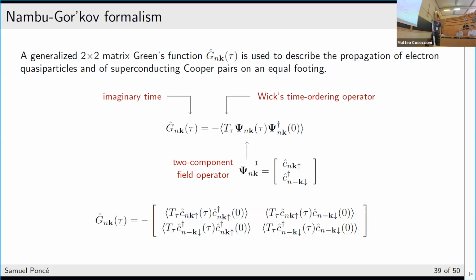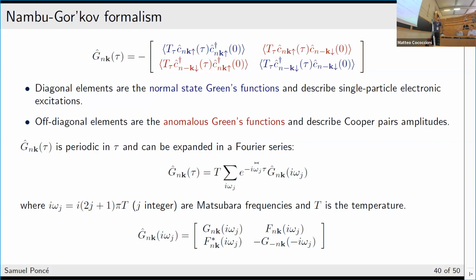One of the important developments is the so-called Nambu-Gor'kov formalism, in which you extend the normal Green's function framework to deal with anomalous Green's functions. So instead of having one function, you now have a 2x2 matrix, and on the diagonal you have your creation and annihilation field operators, but now you also have off-diagonal terms that describe this anomalous propagation, if you want. Basically the diagonal of this generalized Green's function is the normal state Green's function. Those are the ones that describe all the properties that we had before, for example transport, and the propagation of a single particle, the single-particle excitations. While the off-diagonal terms are called the anomalous Green's functions, and they are actually responsible for describing the Cooper pairs,